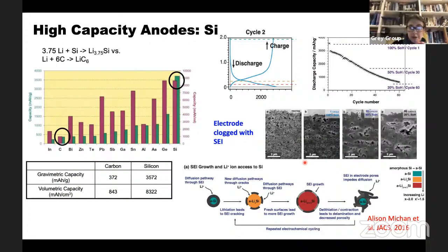Well, the material that's been around for a lot is silicon. And silicon, it's one down on the periodic table, but it reacts very differently with lithium than does carbon. And so one lithium reacts with 6 carbons to form the compound LiC6, while a silicon can react with almost 4 lithiums to form Li3.75 silicon. And so that gives you almost a 10-fold increase, or more than a 10-fold increase, in both volumetric and gravimetric capacity. And so it would be really exciting if you could get silicon to work.